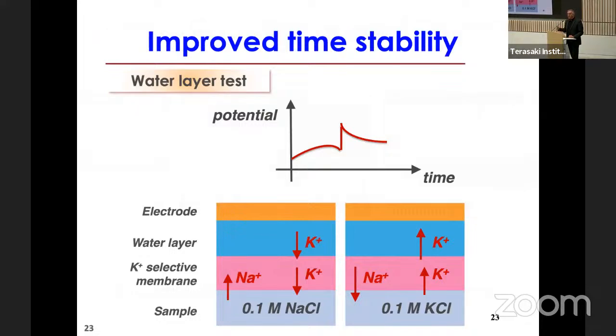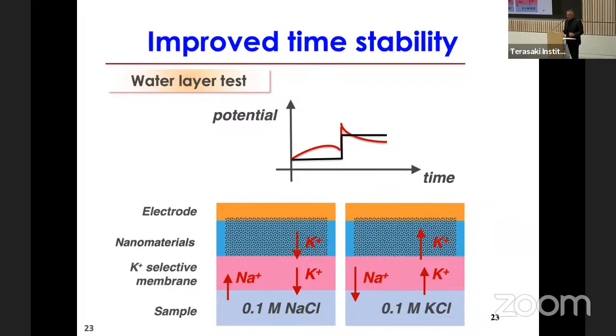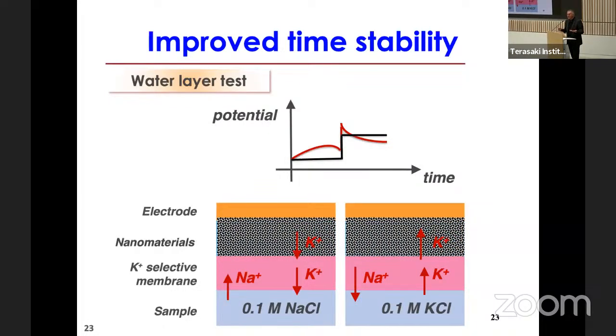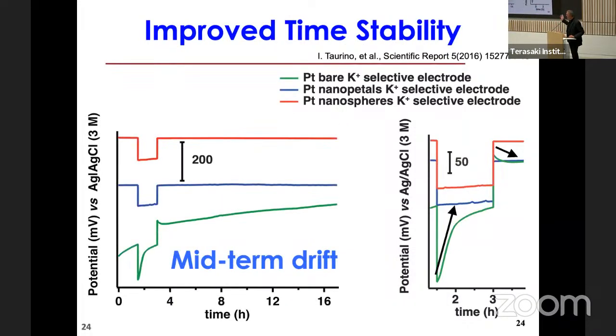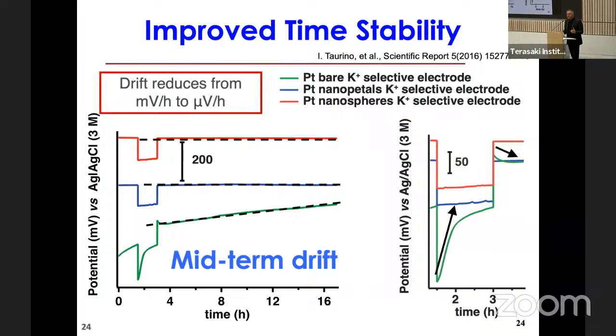With this method, we have also solved the time drift of the ion sensing, because it is known in the literature that the potential is drifting because there is a water layer in between the selective membranes and the electrode. It seems that if we nanostructure the electrode, this water layer is gone, and you can see here clearly how the time stability is highly improved by using nanopetals and nanospheres. So thanks to the nanostructure in the electrode, the ion sensing also became much more reliable.